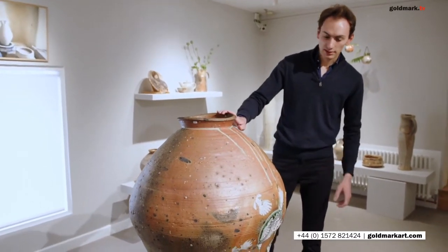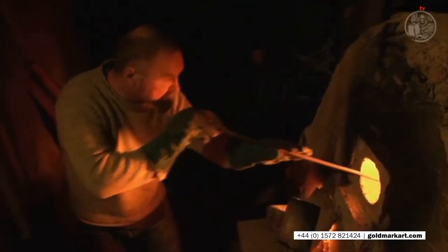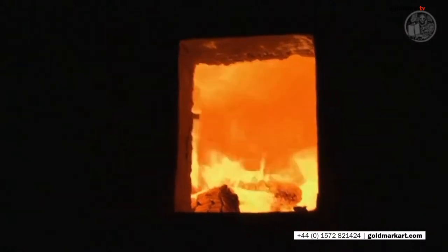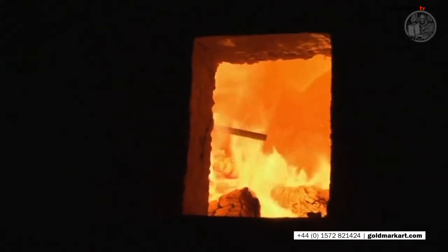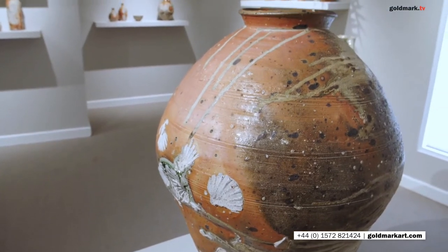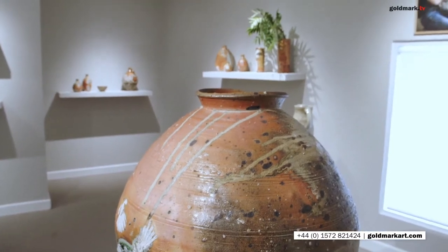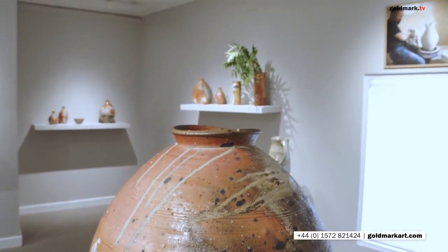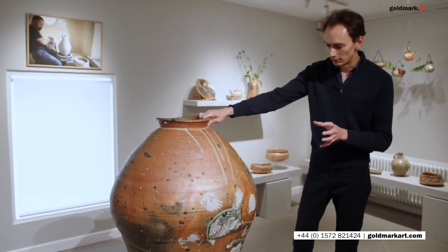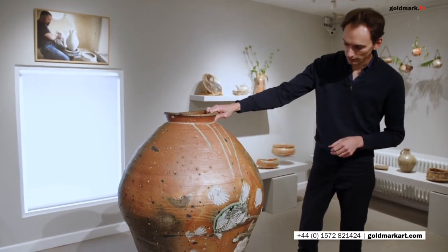Big pots like this wonderful, this magnificent big jar are real survivors. There are few that make it out of a firing in one piece. And you can see the extreme effects of Nick's firings, which can last 4 or 5 days in excess of 1300 degrees. You see the wonderful shape on this pot has started to really warp and distort and sag with the intense heat and the atmosphere at the front of his kiln.